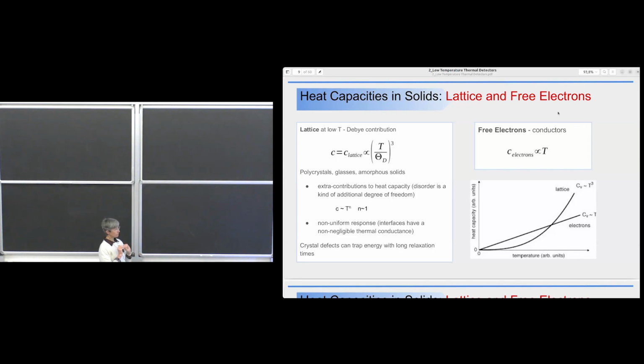So let's now go through a short summary of heat capacities, because this is what we need to know in order to understand exactly which kind of absorber are suitable to build a low temperature detector. So let's concentrate on crystals. If you have a crystal with a lattice, therefore you have atoms or molecules that are organized in a lattice. At low temperature, the heat capacity has this contribution that is called the Debye contribution. This is a parameter that is characteristic of your crystal, and it's called the Debye temperature. You can find it on databases.